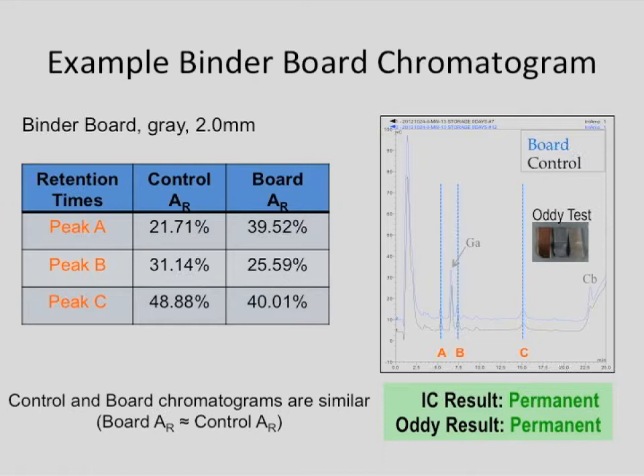Let me show you a few examples of the results we've gotten. This is a binder board that we've aged. The blue line is the binder board, the black line is our control, and here's our Oddy test result. You can see these are nearly overlayable chromatograms, where you do the math of how big these peaks are relative to the galactose internal standard, which is what these percents are, and they're very similar in all cases. So we'd say this is less than 2 times the area of the control sample, and so these are permanent, or usable with the collection.